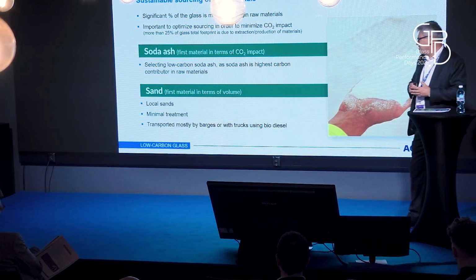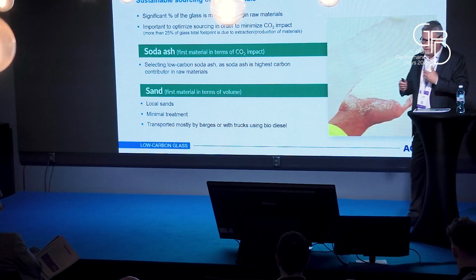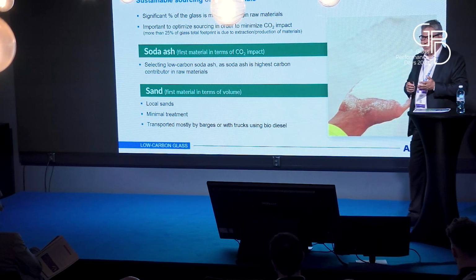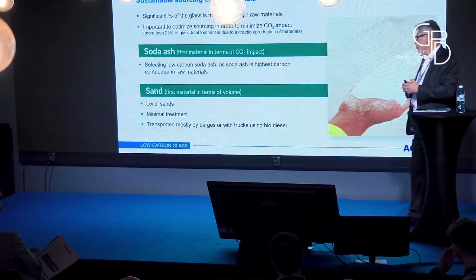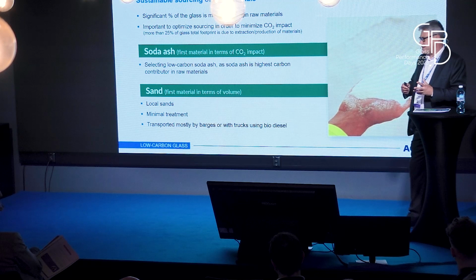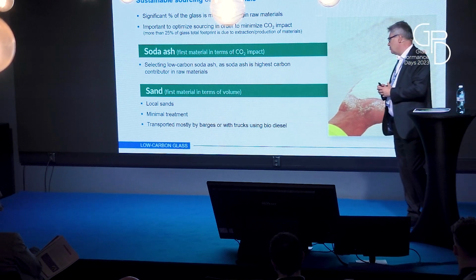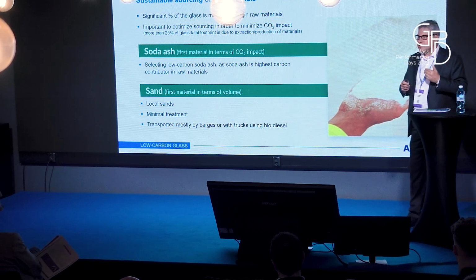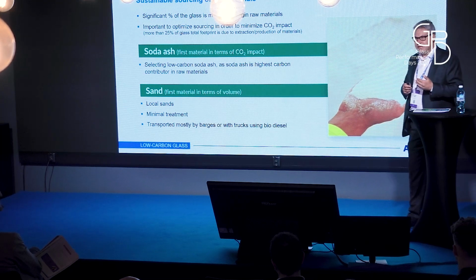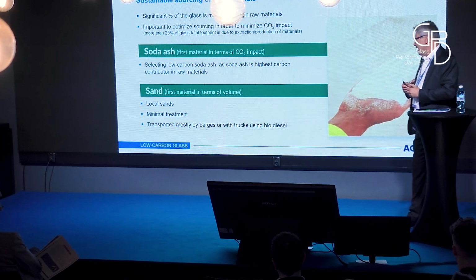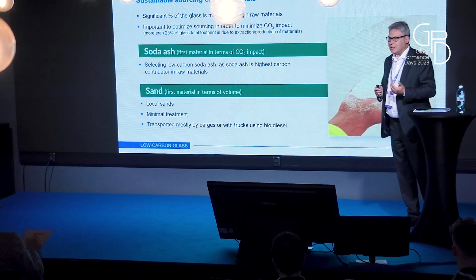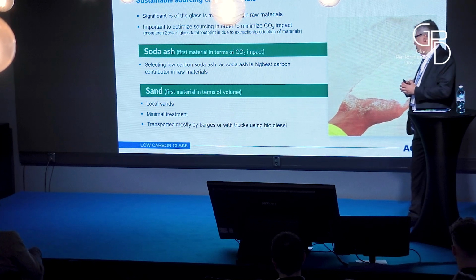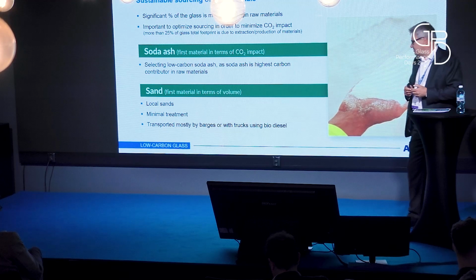The second is the sand. It's the first material in terms of volume, normally at this moment, but as we do not use only cullet, we still have some sand. So we use only local sand. We recommend making minimal treatment, just what is needed to go in the furnace, not too much treatment, not too much refining. And we transport this raw material mainly by barge or by truck with biodiesel.